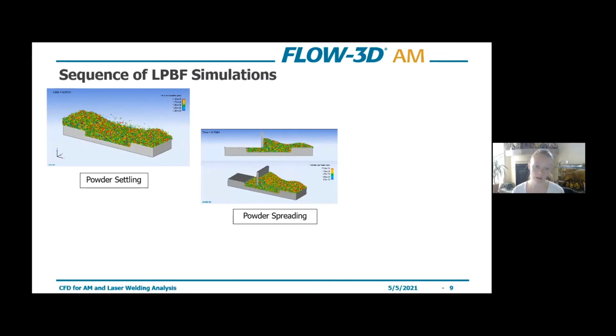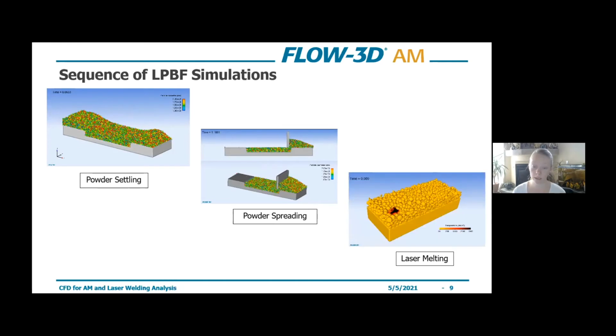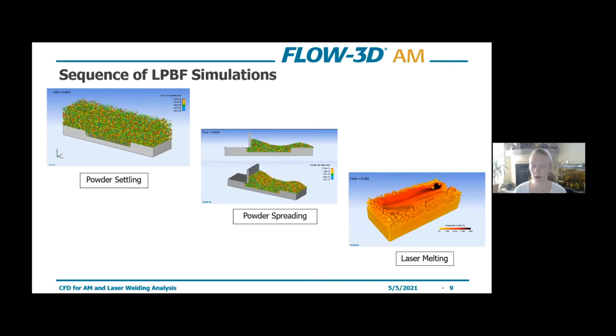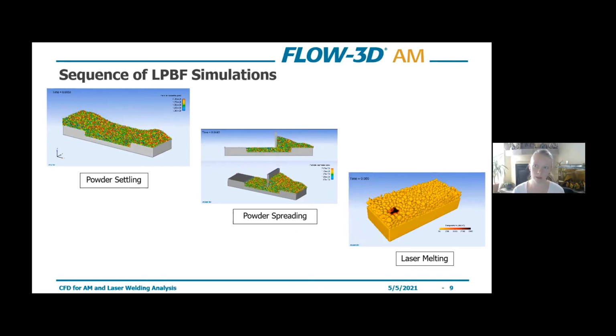So once we've completed this step, this is using the discrete element method. Then we extract that result into an STL, and then we do the melting simulation, where we are preserving all of the voids, all the packing fraction from the powder side of things. The only limitation here is that we aren't accounting for powder movement as it relates to convective currents in the gaseous phase in melting, which can be important, but all of the other phenomena due to Marangoni effects, keyholing, solidification, cooling rates, all of that is captured in these melting simulations.